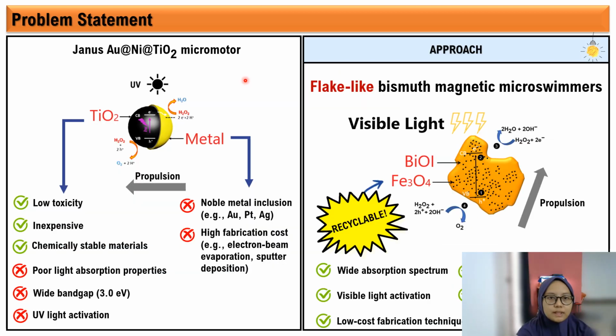A common element used in microswimmers is titanium dioxide since it has low toxicity and is an inexpensive, chemically stable material. However, it has poor light absorption properties, a wide band gap, and needs to be activated by UV light. Moreover, the metal-coated approach to induce a concentration gradient to propel the microswimmers has its own drawbacks since it needs to include noble metals, which are expensive and require complicated fabrication methods such as electron beam evaporation and sputter deposition.